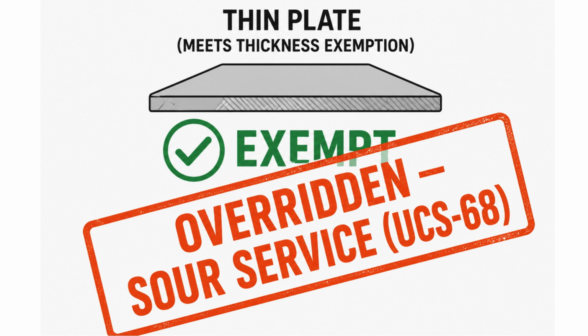But thin metal doesn't always get you out of it. UCS-56 explicitly overrides its own thickness exemptions when PWHT is a service requirement. Sour or wet H2S service under UCS-68 is the classic example. In that case, it doesn't matter how thin your material is or what the table says. The service condition wins, and PWHT is mandatory.